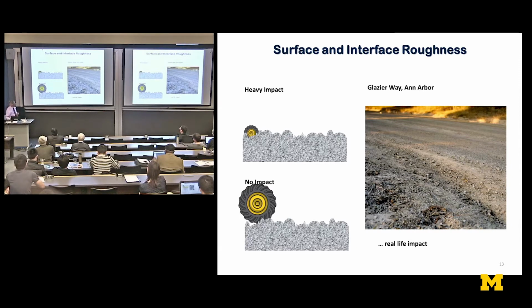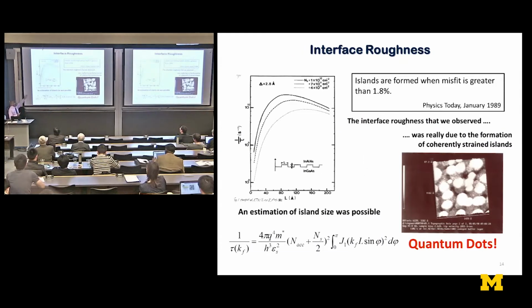And that reminded me of an experiment one of my students had done a few years before that. We were looking at a scattering mechanism called interface roughness scattering in interfaces between two semiconductors and how it affected the luminescence of quantum wells or the performance of transistors and so on. And you can see as the roughness scale comes close to the electron wavelength, the scattering rate goes through a maximum, and therefore the mobility goes through a minimum. And I asked this student, by the way, this student is now one of the presidents of Samsung.